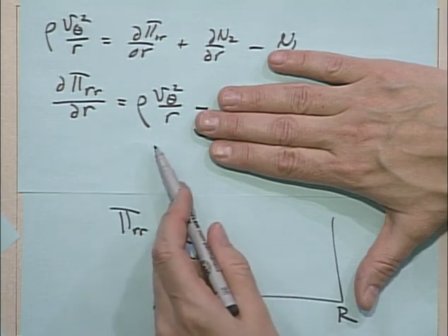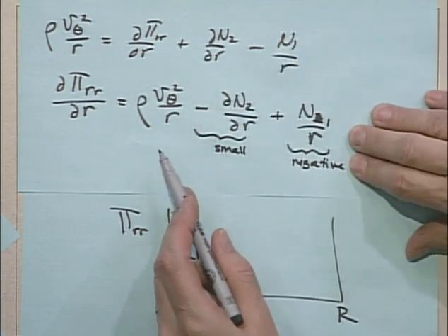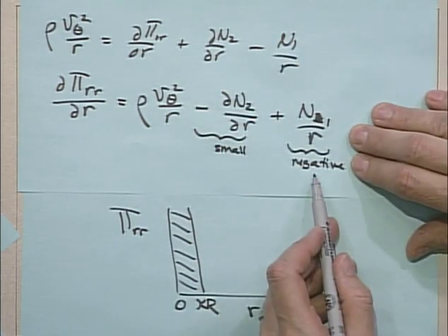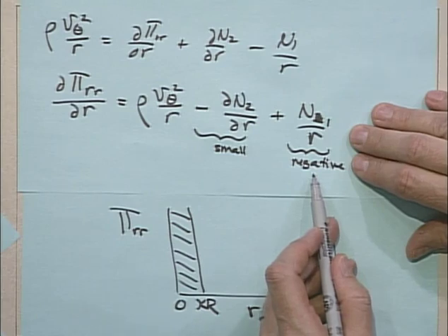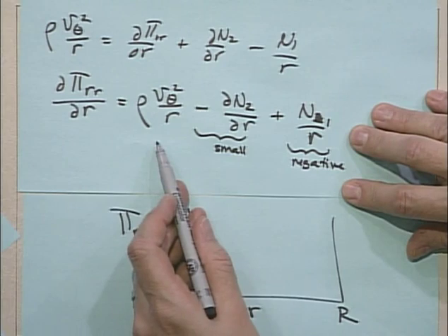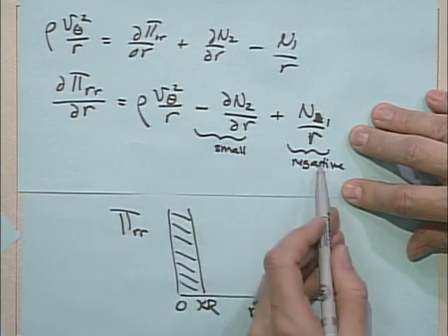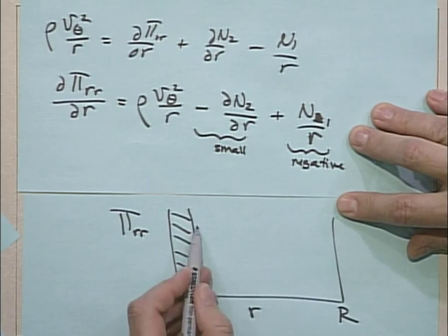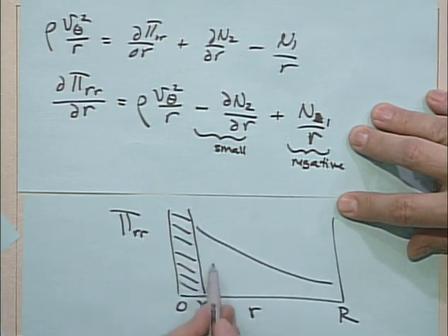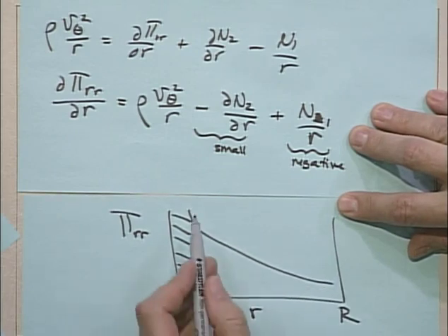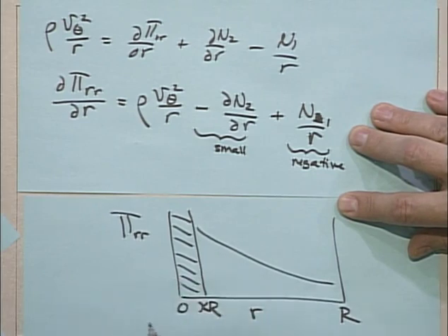For a Newtonian fluid, this term is still positive. But for some non-Newtonian fluids, this term is very large and negative. If it's large enough, if it's polyethylene oxide, if it's polyisobutylene, the inertia is irrelevant, and the thing has a negative slope. There's a net upward pressure on the lid, which indicates that if I didn't enforce the flow to be theta direction, which I have in my solution, there would be a tendency for it to crawl up the rod.